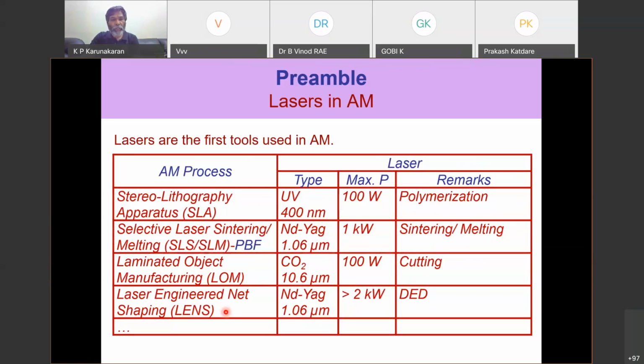Then there is a process called laser engineered net shaping, LENS. This is popular for metals, and it's also very popular for functional gradient metallic objects, because it has 4 nozzles with a central laser. So by controlling the flow rate of the powder in the 4 nozzles, you can go for functionally gradient deposition. So LENS is very popular to that extent. That is known as DED or DMD, direct energy deposition or direct metal deposition.